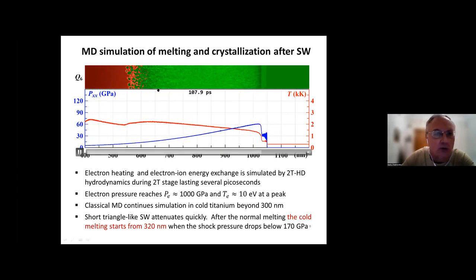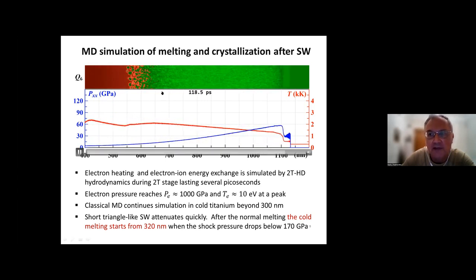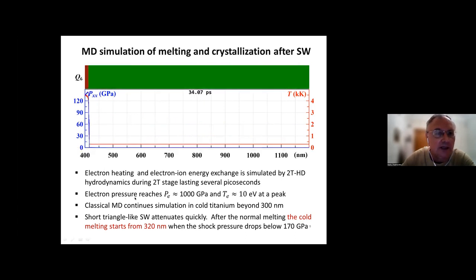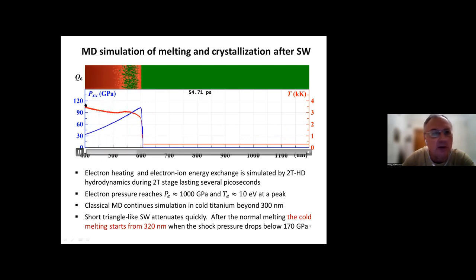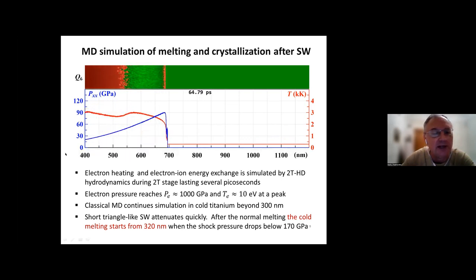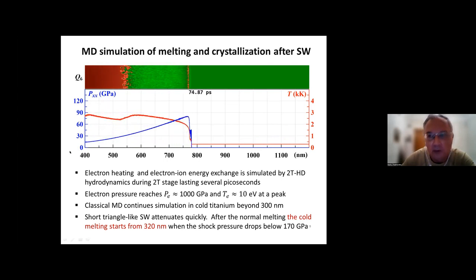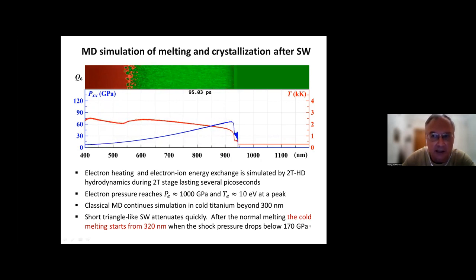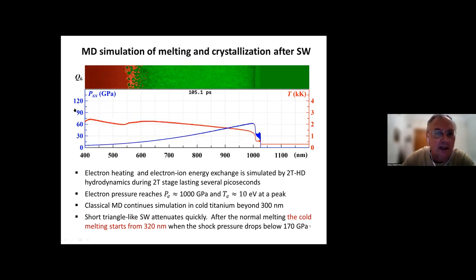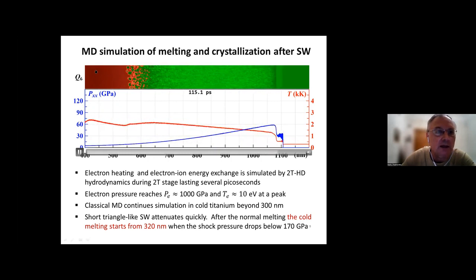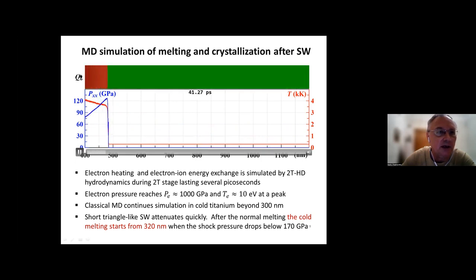However, because the shock wave propagates faster than the electron heat transport, we continue our hydrodynamic simulation beyond 300 nanometers, from somewhere here in almost cold titanium, where the classical MD is definitely applicable. So you see melting, red indicates liquid state by the atomic order parameter, it's called Q6.